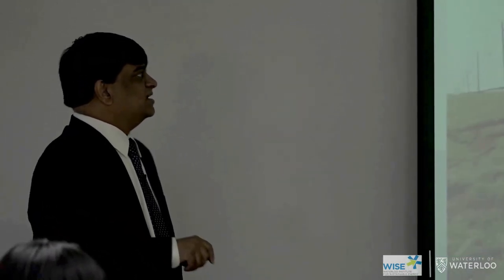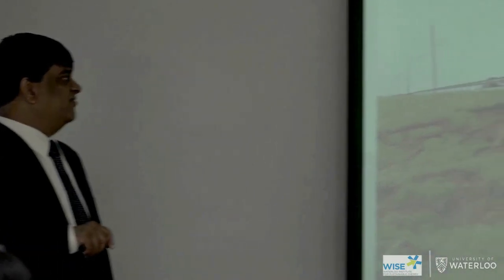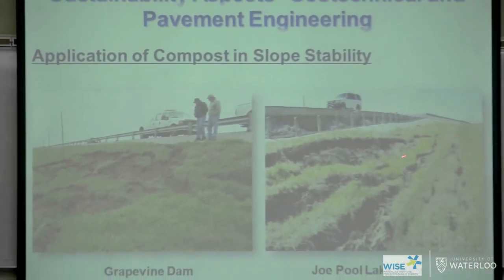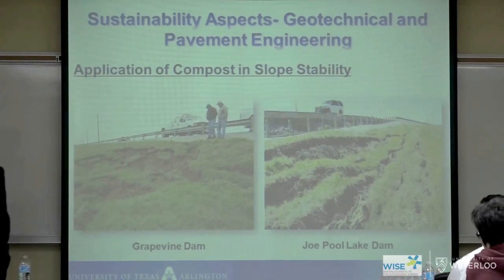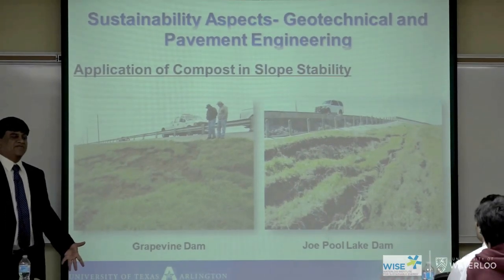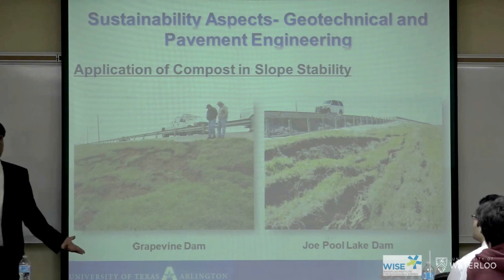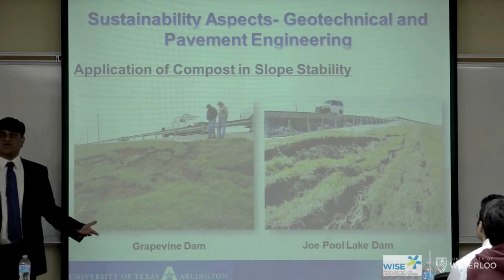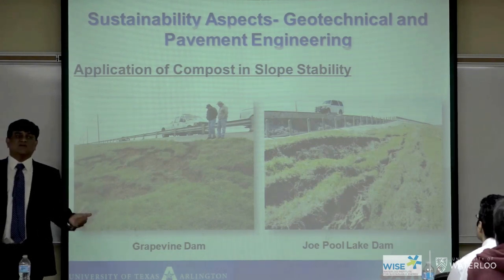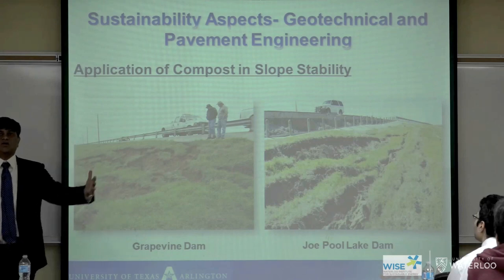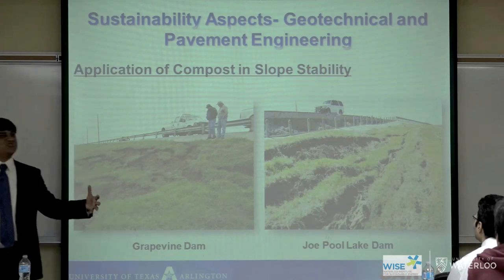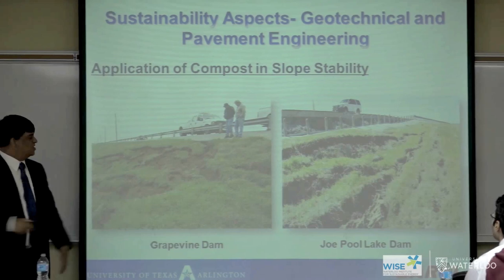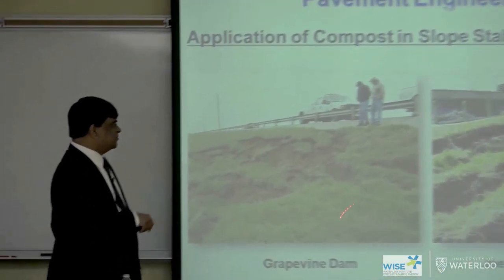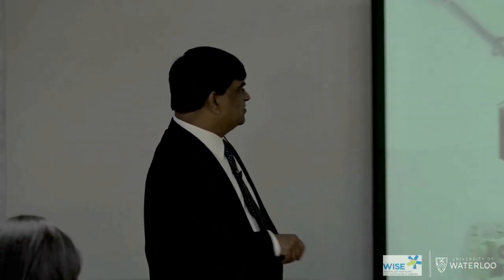This is another major problem in our highways. We have large amounts of cracking. And if you look here, some of our desiccation cracks go up to 5 feet into the ground. 5 feet is like 1.5 meters. So with 1.5 meters of cracks, then first rain, boom, the whole water goes down, the whole material gets soaked and saturated, and you have a slow failure. So we tried to use biosolids compost in this area also, and it worked very well here.